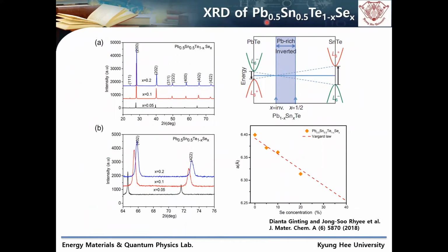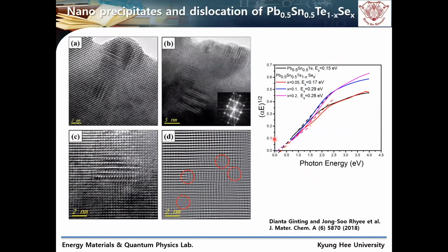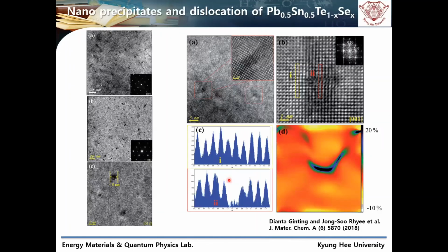One example is the lead tin telluride selenide system. This compound is a Dirac material which has the linear band dispersion, but in this case we adopted selenium doping, and the selenium doping induces the breaking of the Dirac linear band dispersion. We identified that the doping means imperfection or impurities, which breaks the inversion symmetry, and breaking of inversion symmetry gives rise to a topological phase transition.